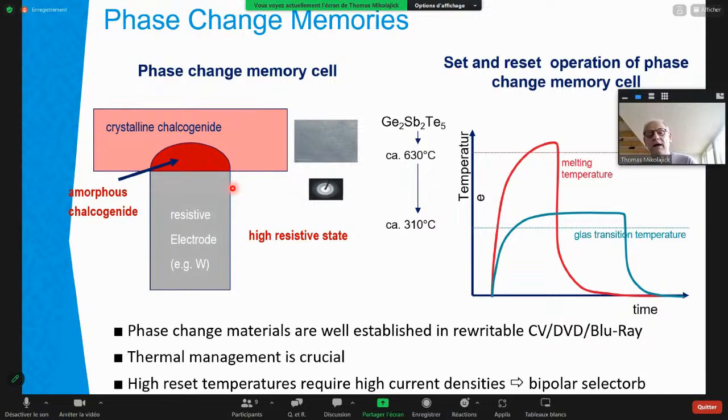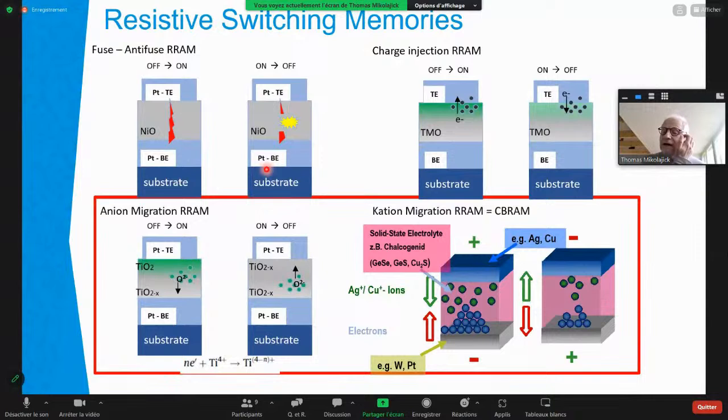And I just saw a very nice demo a few days ago at VLSI technology from ST showing a product for automotive applications. And finally, the ReRAM devices. I already said there are at least four different physical mechanisms. And the more important ones of these are either based on the movement of oxygen vacancies, which at the end lead to a redox reaction in a metal oxide, and then change the valence state of the metal in the metal oxide, and therefore change the conductivity,